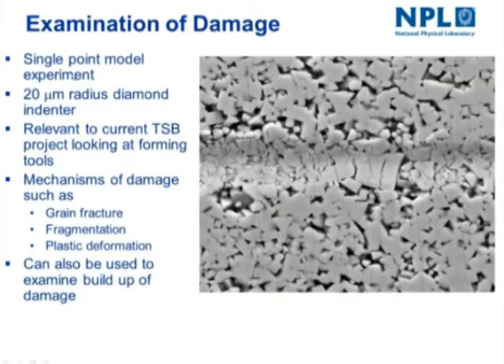One of the important things we do, as I said before, is we look at the mechanisms of damage. And here we're doing a single point model experiment traversing a diamond stylus, 20 microns, across the surface of tungsten carbide cobalt again. You can see the grains of carbide here. You can see the areas where there should be cobalt is etched away in this case. And this is relevant. It says current. That was a year or so ago now.